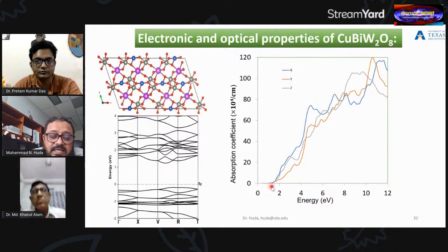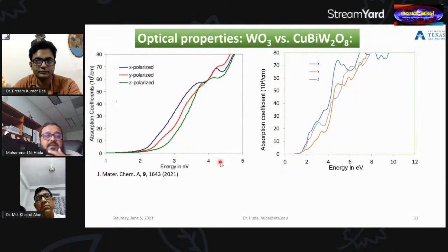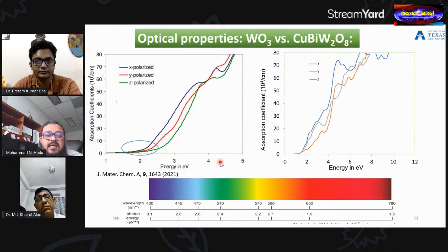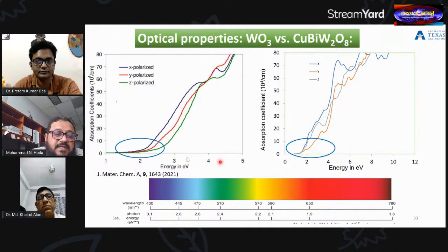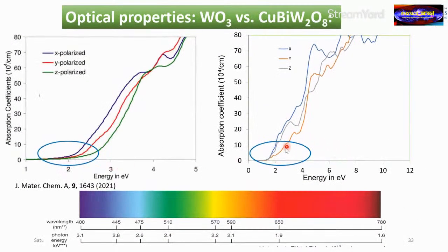Now we can see that here at least the optical absorption started at energy lower than 2 electron volt. In the next slide, we will compare again tungsten oxide and the new alloy. If we focus on here, as you can see, this is tungsten oxide, where the light absorption around 2 eV was almost 0. This is our new alloy, where light absorption at 2 eV has improved significantly in this case.